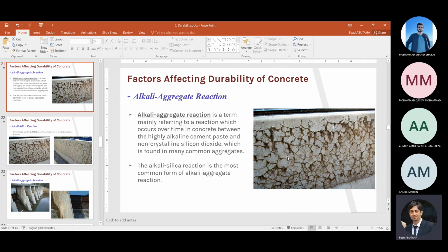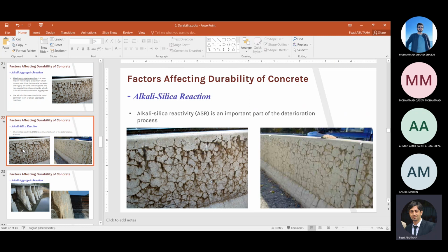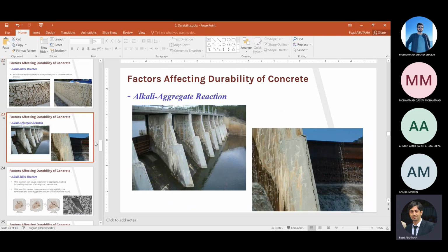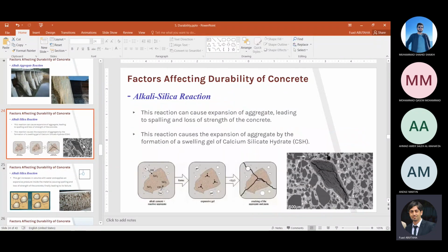So it will end up with cracks, maps, and you might find some gel coming to the surface of this concrete. So these are as a result of the alkaline silica reaction. So what actually happened? This is the particle of the aggregates and it's surrounded with the matrix or the cement base. In the cement, we have alkaline components. This alkaline will start to react with the silica from the aggregate, alkaline silica reaction.